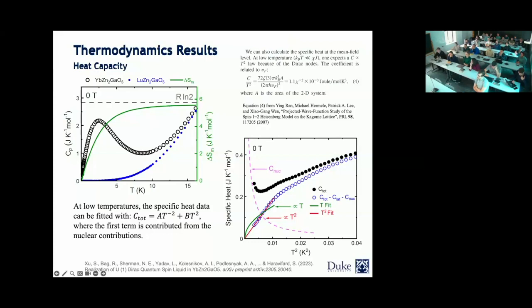Okay. Sorry, just to clarify. The confusing thing to those of us innocent theorists is how well established is the C nuclear line? Right. So when we fitted this, we checked against other compounds that have ytterbium 3+ in them, and the value is in very good agreement with that. Other compounds where people have seen the nuclear contributions for ytterbium completely agree with the values that we get for A. This is the first term for the nuclear.